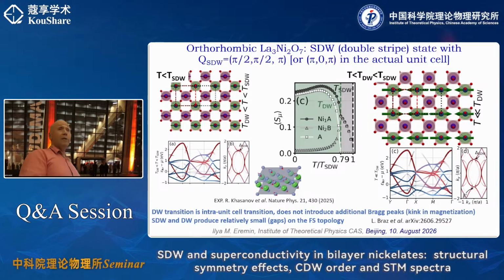So the only other order that we allowed is the intra-unit cell charge order. We allowed this order to develop, and indeed in this case we see that it develops at low temperature. However, we don't see this order at high temperature. When we compute the charge instability at weak coupling, we don't see it. However, once we perform a reconstruction of the fermiology, we see that both charge and spin susceptibility develop a Q equal to 0 instability. That is this intra-unit cell charge order. It's partially a result of the folding: there are these regions, and there is some scattering between these regions at low Q, and that gives rise to the additional charge modulation. However, it's not something very conclusive, I would say.